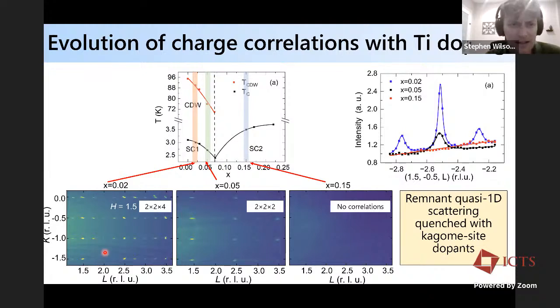is something different. At light doping, you just see this 2 by 2 by 4 state, as well as 2 by 2 by 2 correlations. When you dope it a bit heavier, then you just see 2 by 2 by 2 correlations. But then when you get out into the second superconducting region, where there's no thermodynamic anomaly associated with the charge density wave state anymore, then we see no charge correlations. And so our current picture of this is that the remnant quasi 1D scattering we saw in the Ti doped system is quenched due to putting the disorder onto the Kagome sites. That's our current model, but we're still exploring that further.